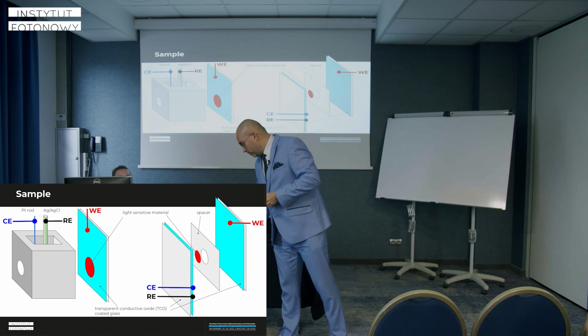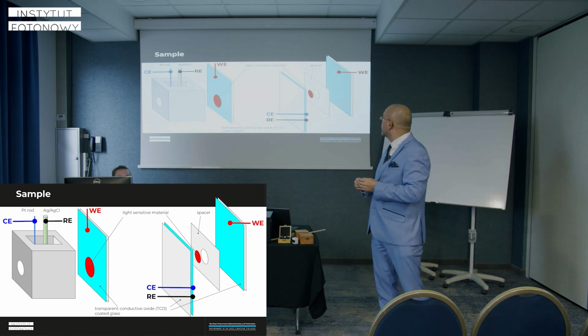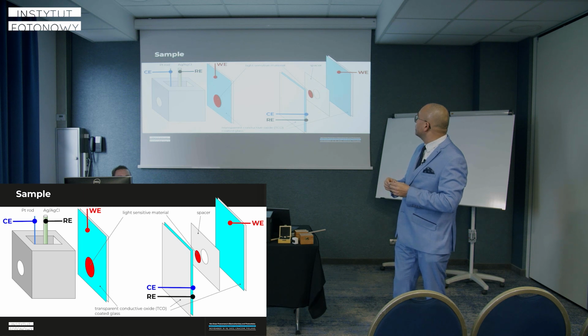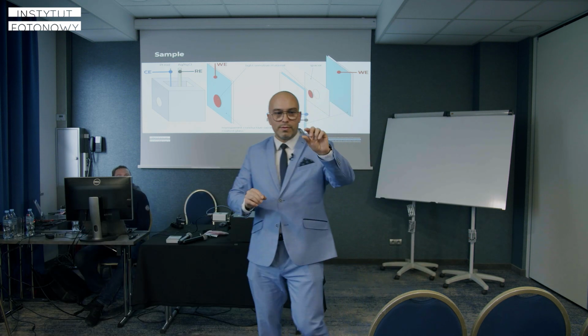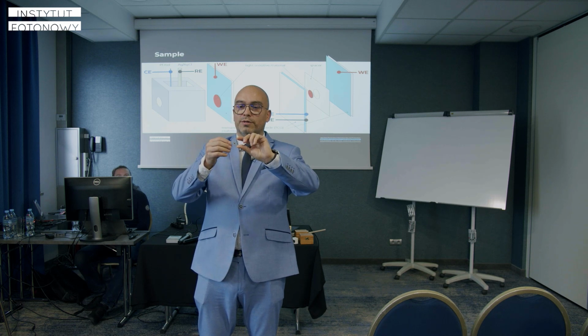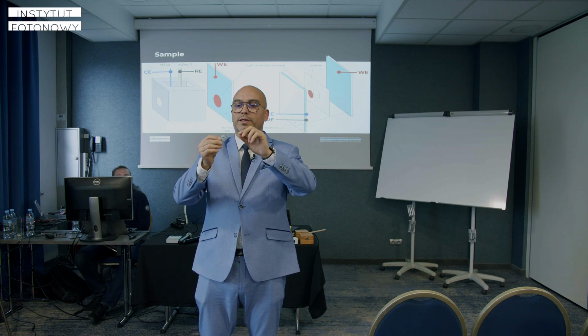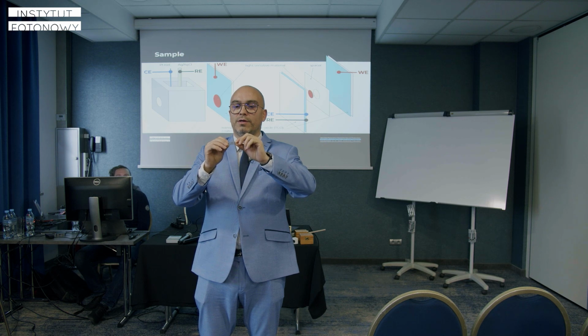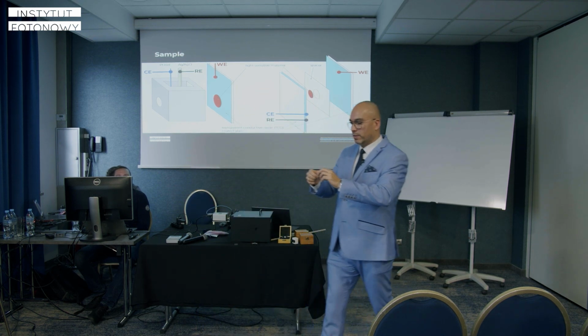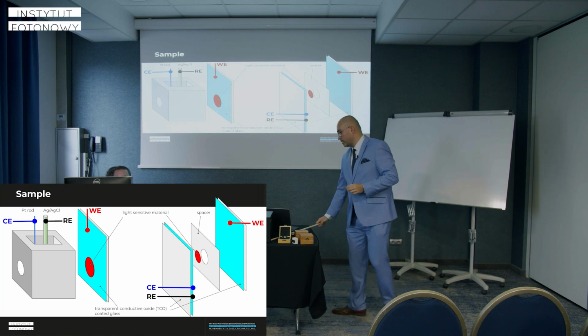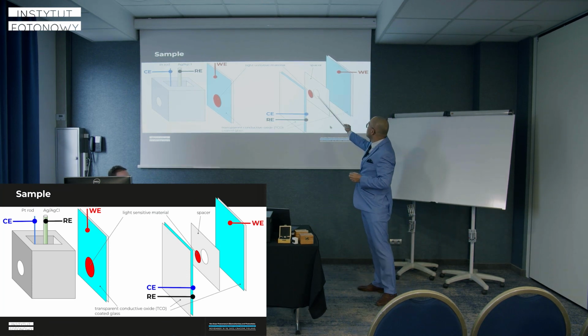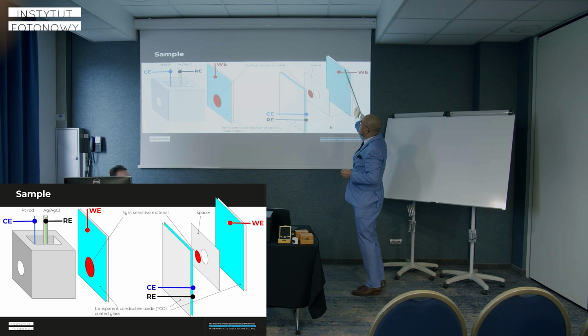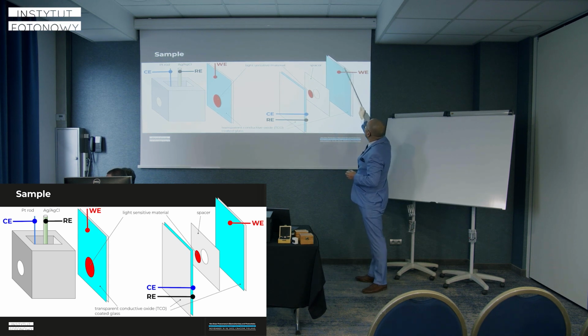Another way is to use two glass plates like this. There are two glass substrates with ITO or FTO, and between them we place the sample with an insulating spacer, and then we just clamp with a crocodile clip here and two electrodes here, and the current flows through the sample from one electrode to the other.